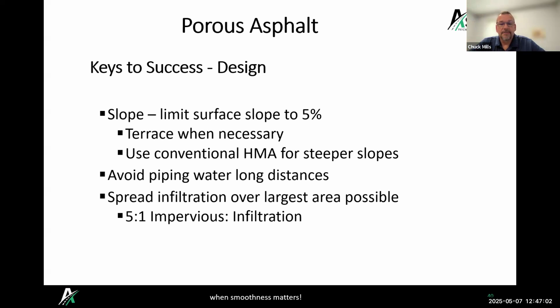We want to avoid piping water long distances, so you want to look for and spread that infiltration over the largest area possible. 5-to-1 is a rule of thumb, impervious to infiltration area. So a lot of that comes down to looking at all the water that you're collecting into this porous system and where it's going to go and how long it's going to take to get it out of there.